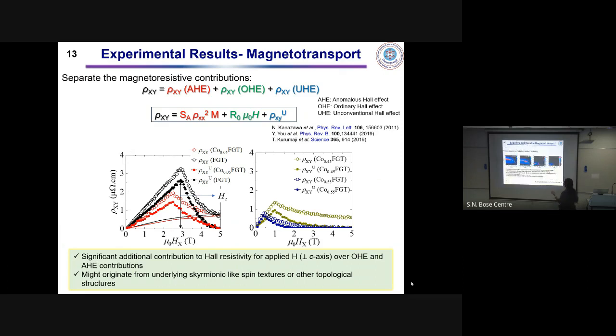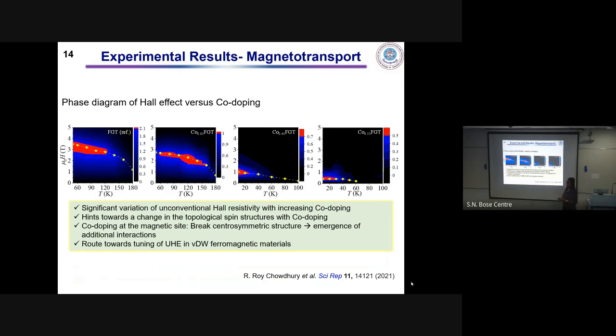So this is the main part of the result that we have observed. Now we finally constructed the phase diagram of the Hall effect versus the doping. We did a contour map of the magnetic field, the temperature, and the maximum value of the transverse resistivity, the additional contribution, the unconventional Hall part, and we could see a significant variation of the unconventional Hall resistivity with increasing cobalt doping. But why don't you call it a topological Hall? I can call it a topological Hall effect, just that from the data I had at that time, I could not separate out the skyrmions and the magnetic domain.